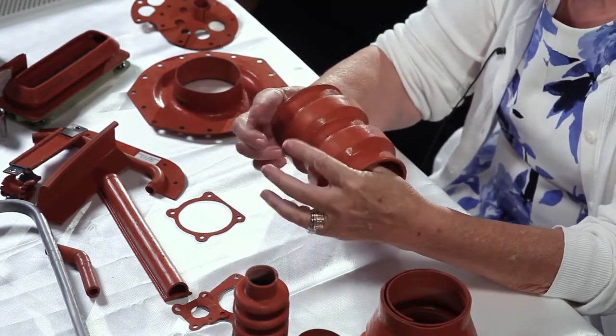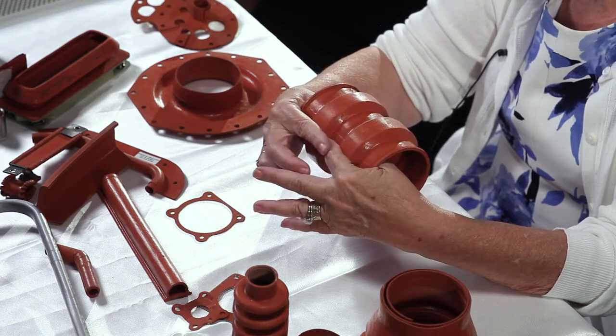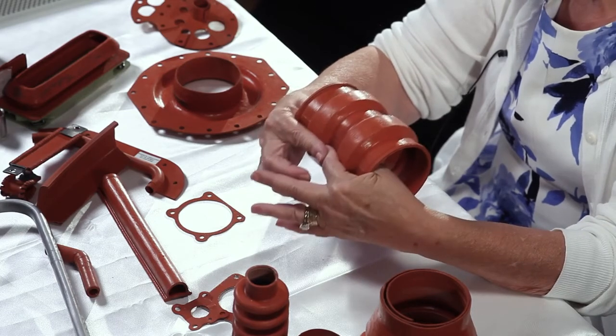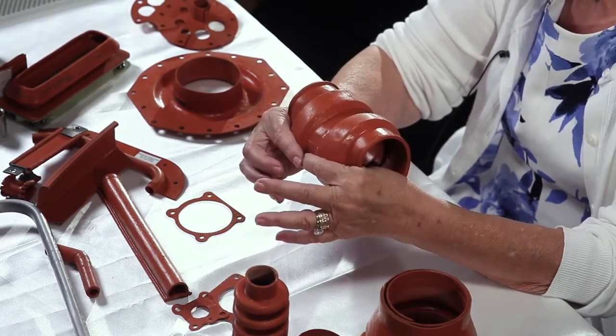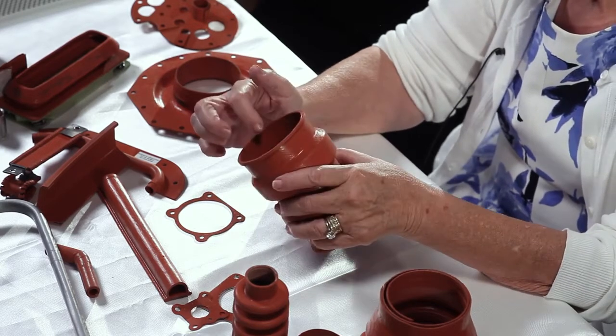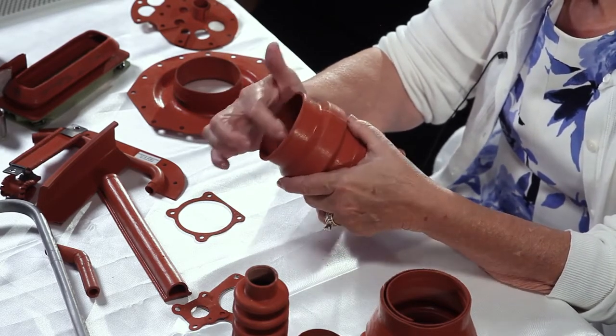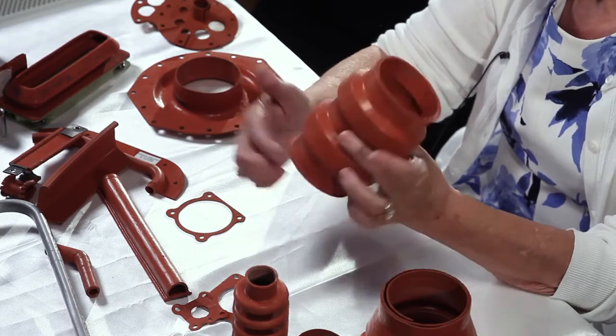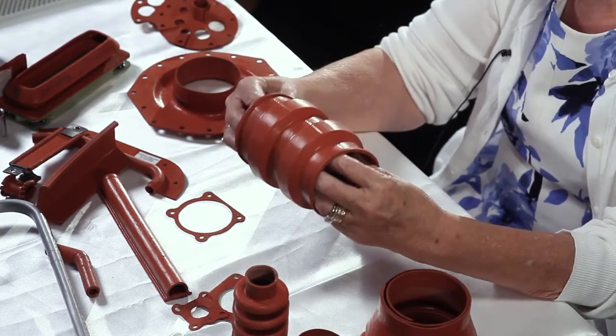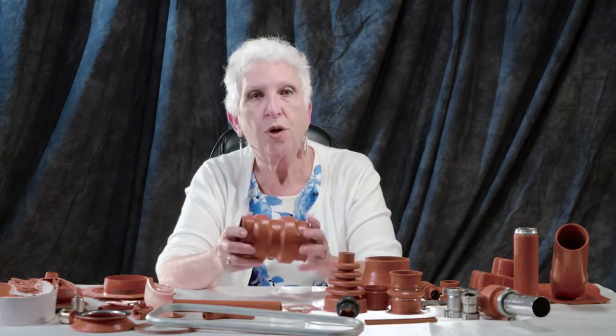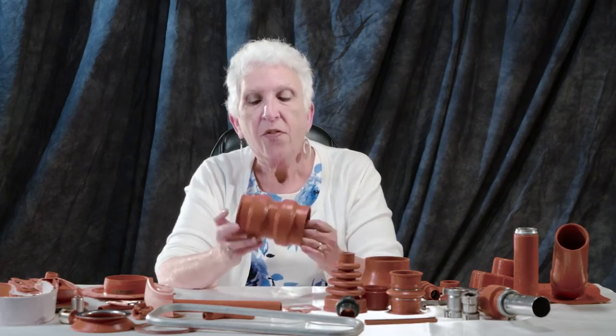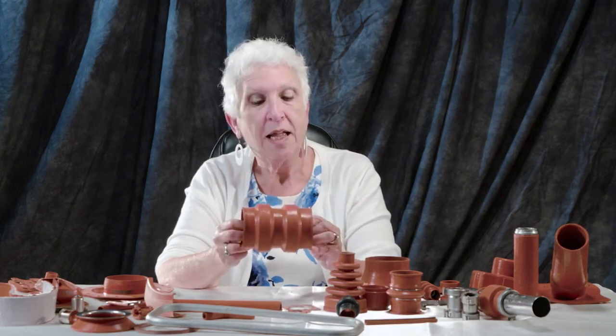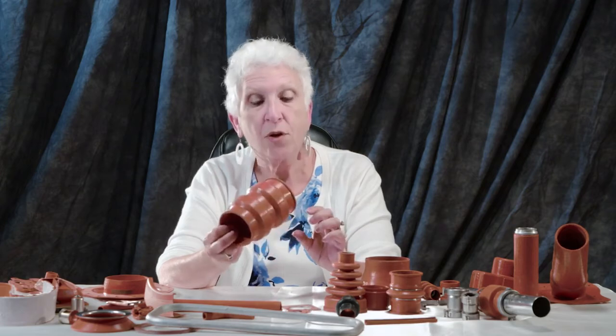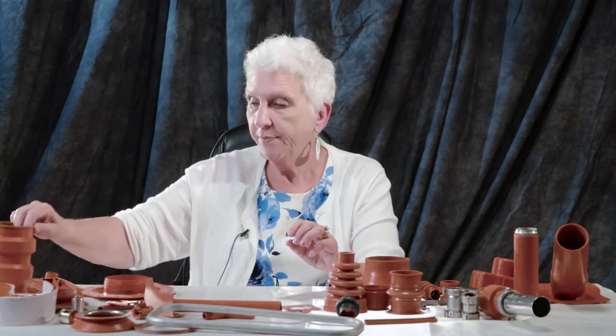In the set, it's actually two pieces of tape. They are overlapped in the center so that we have flexibility without losing conductivity. And we allow for 3 to 4 openings in the ID on each side. So you have complete contact, and the material is encapsulated so you cannot damage it or lose contact. These parts are 787 air management ducting and have been working very well. We have never lost conductivity in a part.